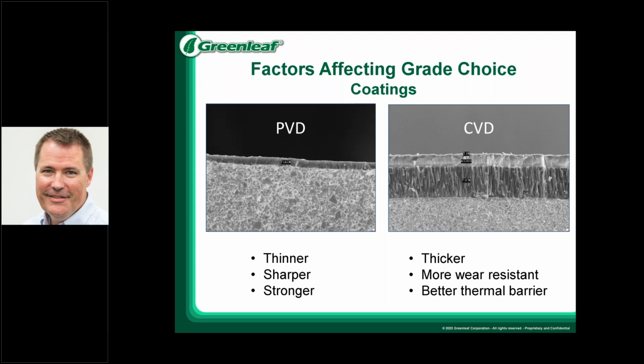CVD coatings are much thicker, typically with multiple layers like shown here. They offer more wear resistance and provide a better thermal barrier to the substrate below. You're not able to have as sharp of an edge typically with CVD coatings because they are much thicker than a PVD. So when looking at your materials that you're machining, it's important to understand what you're looking to accomplish. If you need to have that sharp edge for better shearing of material, you probably likely need to be with a PVD coating versus CVD. CVD works very well for roughing applications.